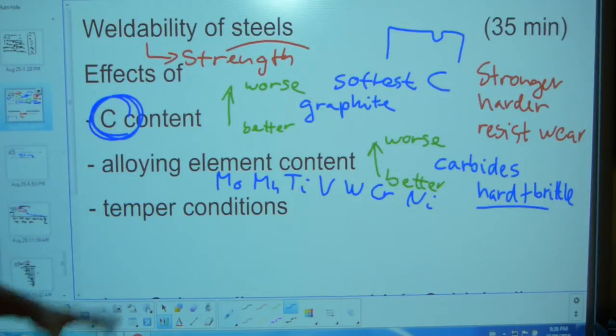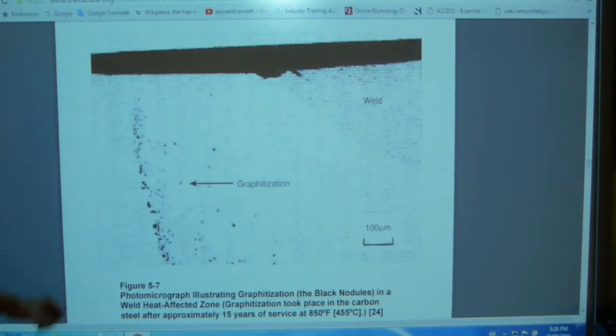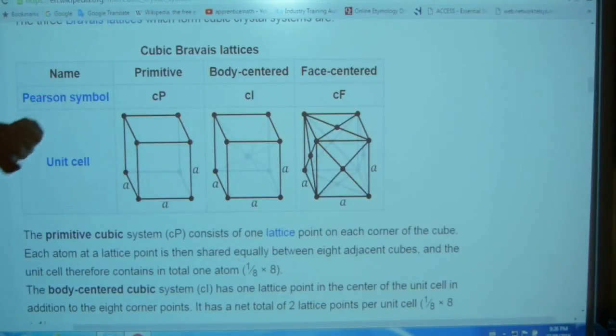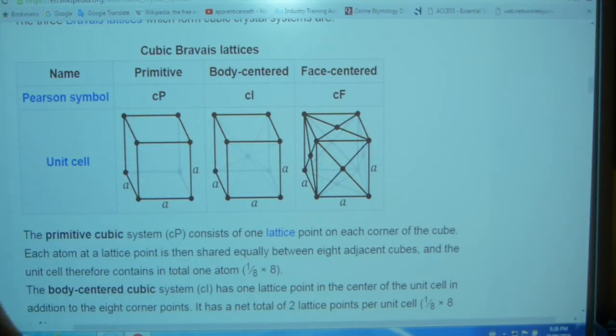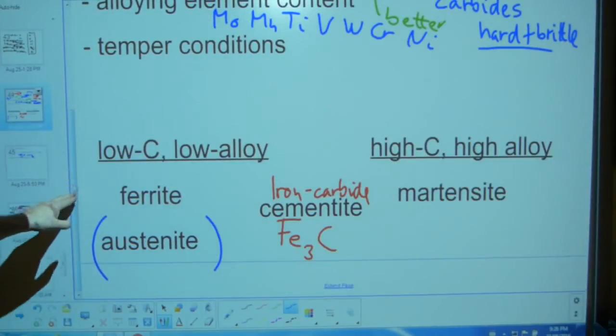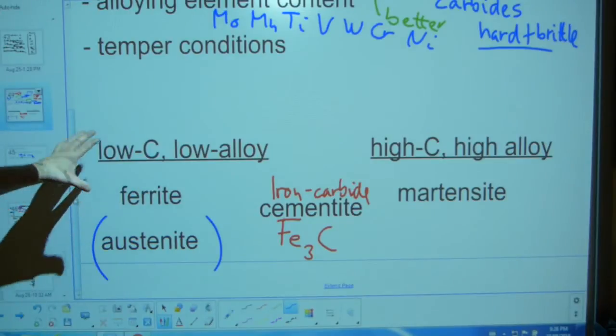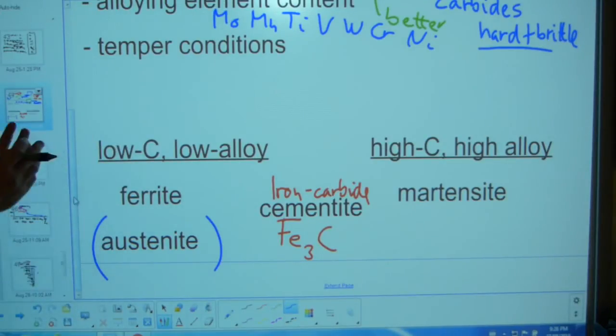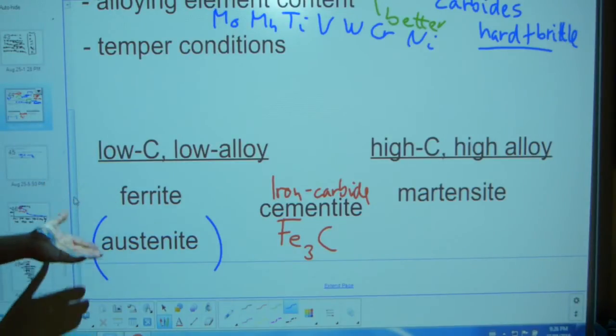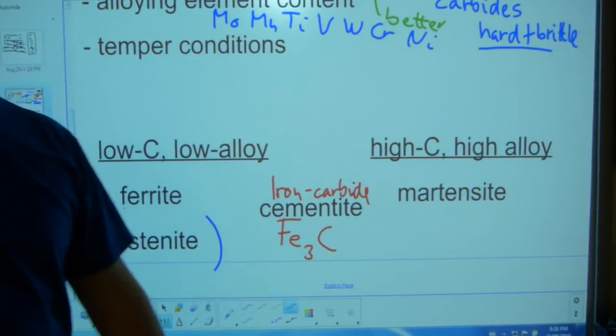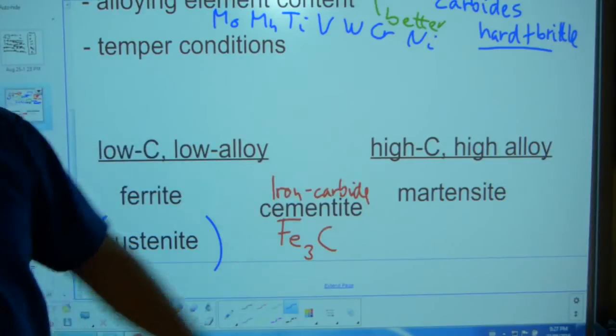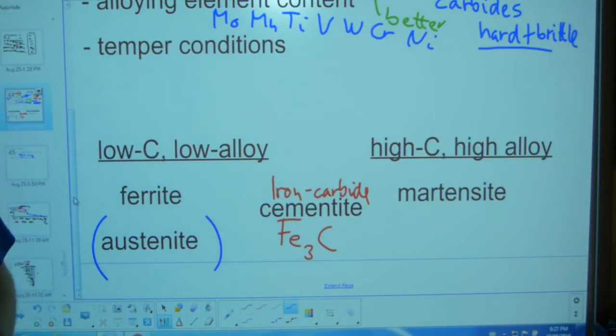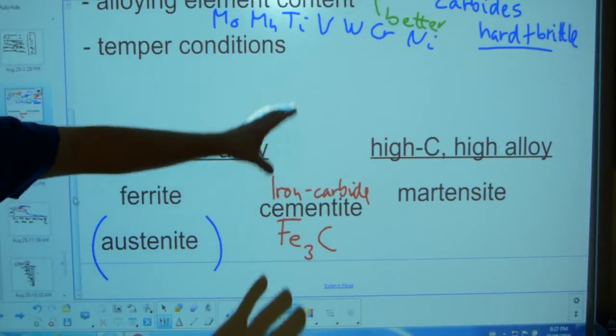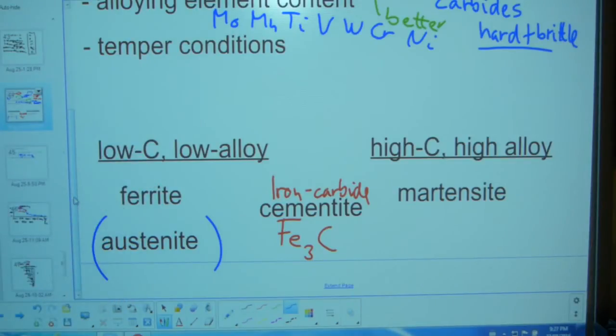Last one is temper conditions, and temper conditions need a little bit of explanation on these crystal lattices that are over here. Austenite is face-centered cubic, and martensite is body-centered cubic. Over here, I've got this kind of stuff. Austenite here, martensite there. Low carbon, low alloy steels, as they cool and solidify from liquid state, form ferrites and austenites. When you have high carbon or high alloy content steel, as it solidifies, especially when it's quenched, but even at lower rates of cooling, it produces a lot of martensite and some austenite and very little ferrite.